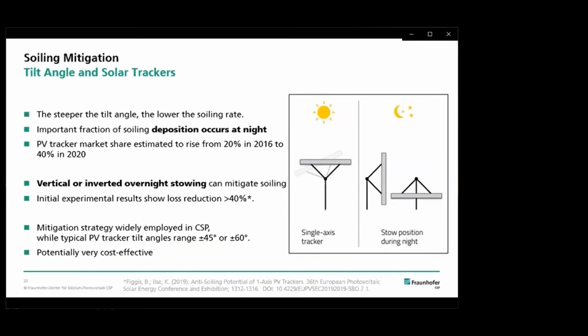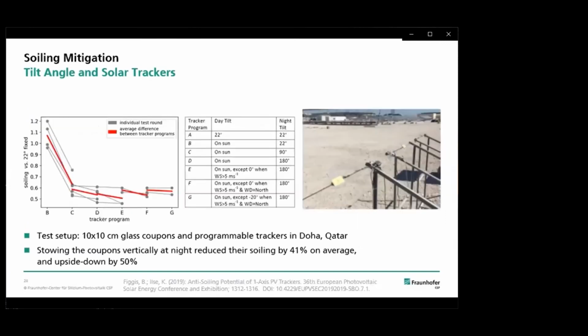So we've seen that if one uses, for example, nighttime stowing at 90 degree or 180 degree, one can decrease the soiling rate by more than 40%, which we have also seen in outdoor experiments. This mitigation strategy is also widely employed in concentrated solar power. However, the typical PV trackers which are there on the market have only angle ranges between 45 and 60 degrees. So it still needs to be checked how cost-effective one can adopt.